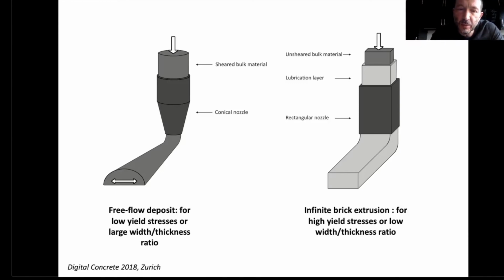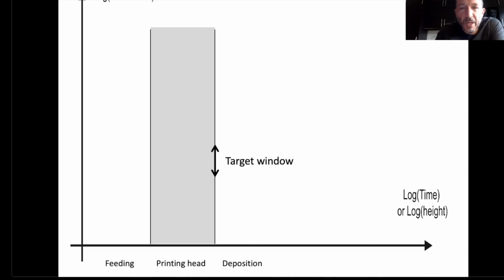We have two cases. Some people do free flow deposit where the material is very fluid and then builds up a structure because of thixotropy, nucleation, structuration. And on the other hand, you have people printing in a mode that is called infinite brick extrusion, where the material yield stress is quite high, and the material shape is mostly controlled by the initial consistency of the product. Well, here we have, at the level of the deposition, a target window for yield stress.